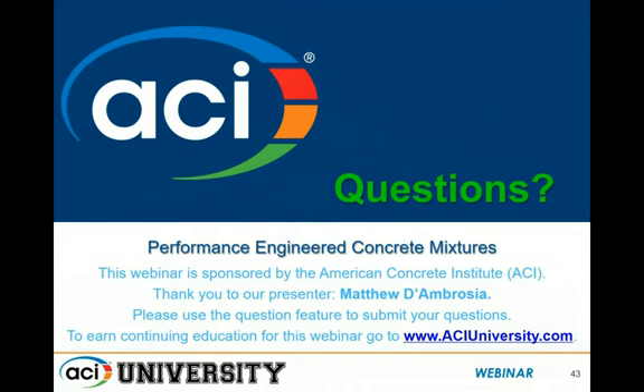So that probably is why compatibility of strength is mentioned, because historically that's how you come up with the modulus. But I would really advocate measuring the modulus directly rather than trying to predict it from the strength, because I see many ways, especially in this program, many of the strategies that we employed can change that relationship between strength and modulus. So you don't want to lose sight of what's really critical, which is the stress development.